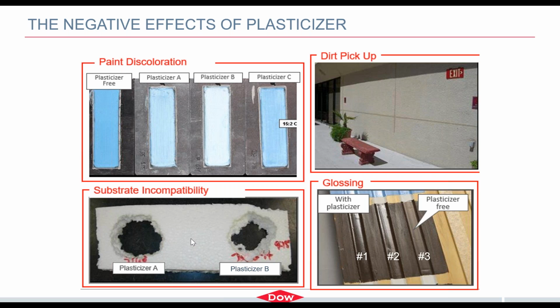I also mentioned substrate incompatibility for construction products. This is expanded polystyrene foam, and I basically took a drop of 2 different plasticizers, put it on the foam, and just let it sit there in lab over time. And time on this is weeks, if not months, and the hole just kept getting bigger and bigger. So this is another reason, depending on your application, why you would want a plasticizer-free sealant.